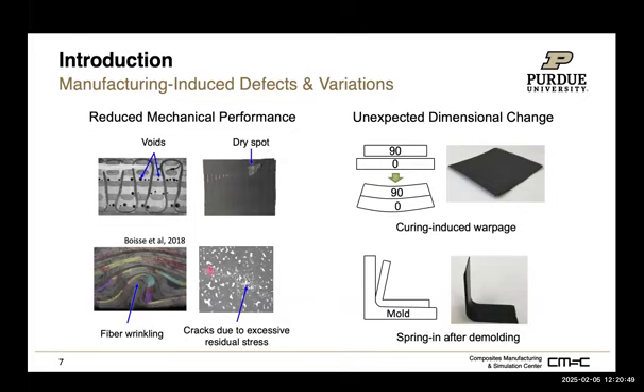And there are also cases where, maybe not very significant, but if you pay attention, I think with the zoom you probably can see on the screen, cracks have actually developed. Those cracks are not because you applied mechanical loading to break the part. It is because the curing process generates lots of heat, and that heat can introduce large enough residual stress that eventually develops micro cracking in the polymer.